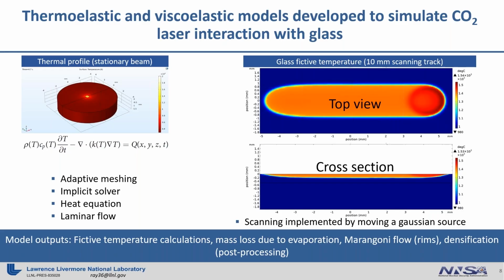And what we see in the top panel there is the bird's eye view of a fused silica, where a Gaussian beam started on the left side and raster scanned across to the right side. And it's abruptly shut off on the right side where you see that red circle. And so it has a very different cool down there where the laser abruptly shuts off versus traveling on through. So we see that reflected in the fictive temperature. And in the bottom panel is just a cross section. So the model outputs are the fictive temperature that we see here, mass loss due to evaporation, which is included within laminar flow and a microfluidics module, and Marangoni flow, and densification. And I'll show you in a slide or two that densification is done post-processing, which really helps with the simulation time.